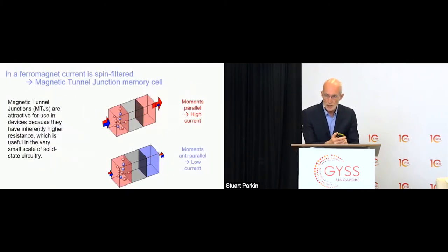Now it turns out the same device where we replace copper by an insulating material turns out to have larger values of magnetoresistance. The physics now has nothing to do with giant magnetoresistance and spin-dependent scattering. It's due to spin-dependent tunneling. So in this cartoon, you can see two red layers, two magnetic layers with their moments parallel, separated by an ultra-thin insulating layer, shown in gray. And this will be approximately 1 nanometer thick.